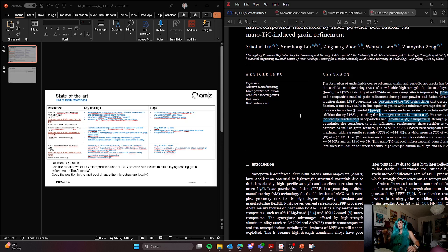They found actually that it's the process of dissolution and solidification of this titanium carbide that led to the formation and precipitation of this cubic phase of L12 aluminium 3 titanium. This one is mostly used and found as a nucleating site. And not only with that, but also with lamellar aluminium 4 carbon 3.